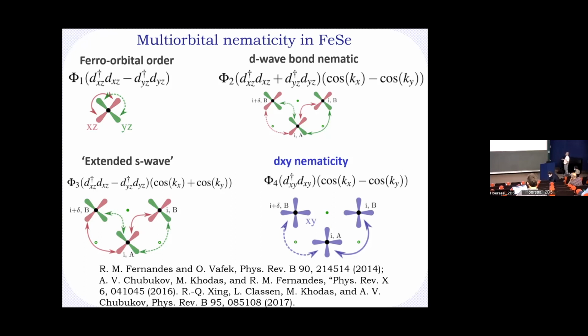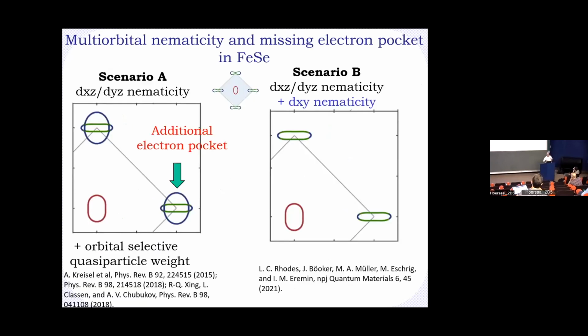And actually, there has been an RG calculation which showed that, at least according to the RG, you have either these 3 order parameters dominant and this one very small, or the other way around, where the DXY nematicity essentially is dominating. Now, it turns out that the experimental situation is more complicated, because if you take the view that there are only these 3 order parameters,